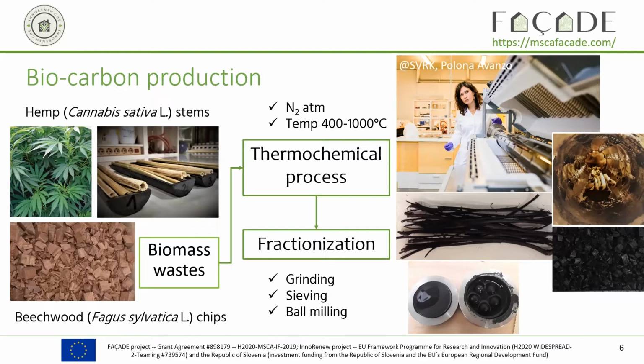So a thermochemical process, you can see on the right a picture of the tube furnace. We will use a nitrogen environment and temperature ranging from 400 to 1000 degrees. And it will be classified as slow pyrolysis or carbonization type of thermochemical process. After we obtain this carbonized biomass, we will fractionize it. So we will grind it and sieve it into different particle sizes, and we can also further downsize using ball milling in liquid state, and then we will dry the material to get a powder.